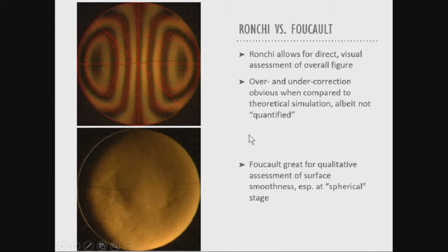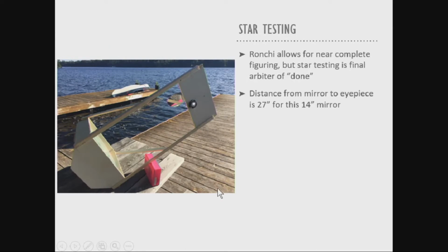Conversely, the Foucault, which is normally something that you would actually do measurements on, is difficult to do for fast mirrors. However, you can still use it as a qualitative tool to assess your general surface shape. So this should be spherical, this should be all uniformly shaded, and you can see there's actually some pretty grody roughness here. So it's good for doing smoothness tests. Ultimately, you do the Ronchi test for as long as you can. Ultimately, though, the final arbiter of how good your mirror is is the star test. And the star test allows you to really assess the level of doneness.